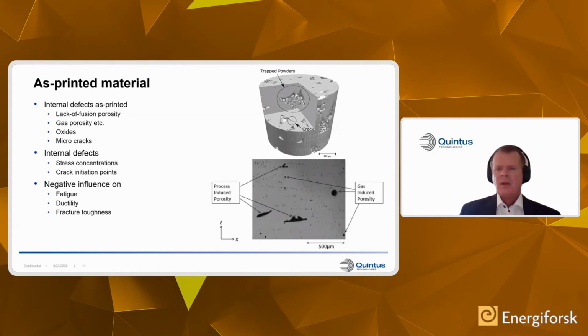Typically, as printed materials, we could have a number of defects. What we are looking at is porosity, oxides, and microcracks. And obviously, these defects will have a negative influence on mechanical properties like fatigue, ductility, and also fracture toughness.